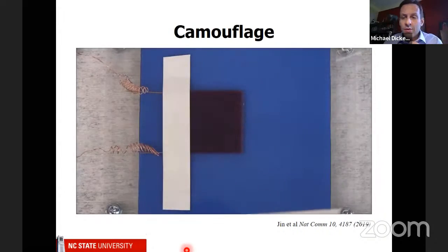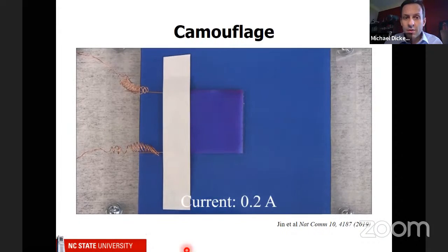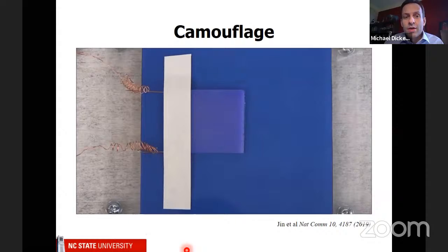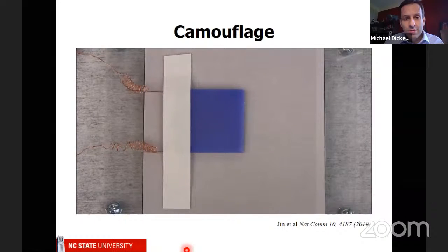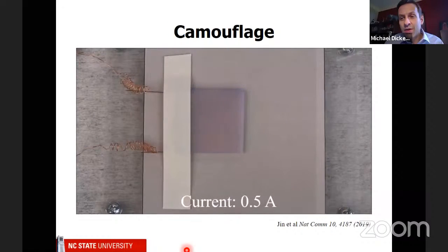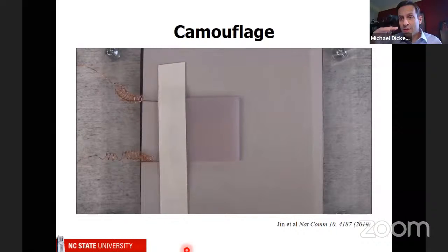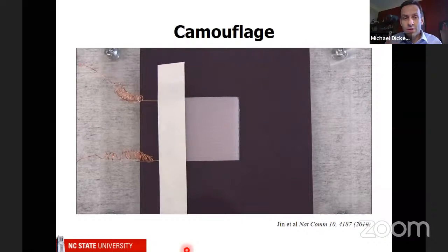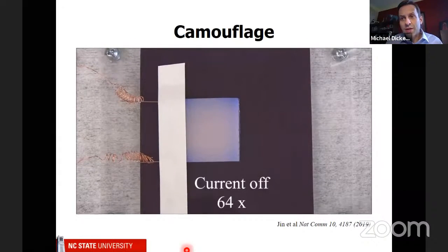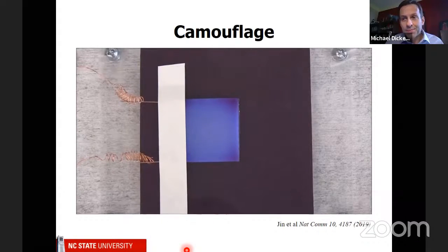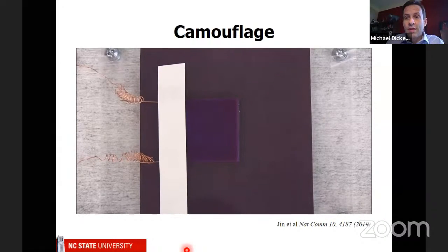And so if you apply a little bit of current, you can make the red disappear, and so it appears blue. And if you apply more current, you can get the blue to disappear. Now it appears white. So this is simply taking it to different temperatures. And now if you let it cool back down, those colors will come back. Okay, so the basic idea is we're using temperature to cause a change in color.